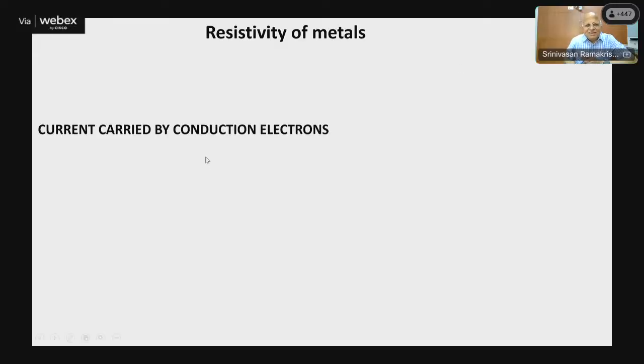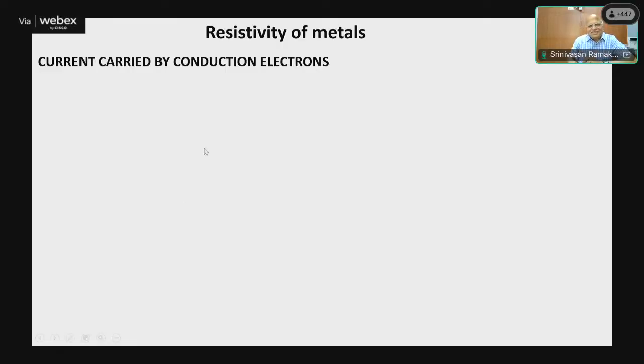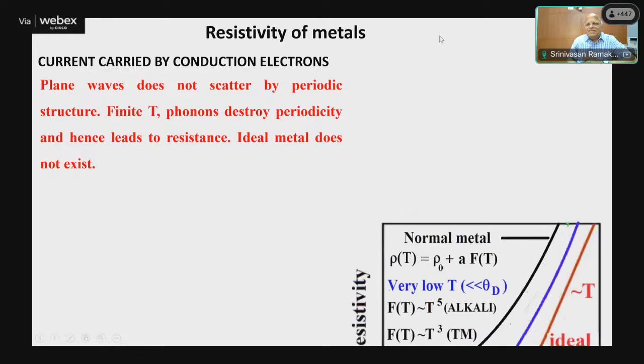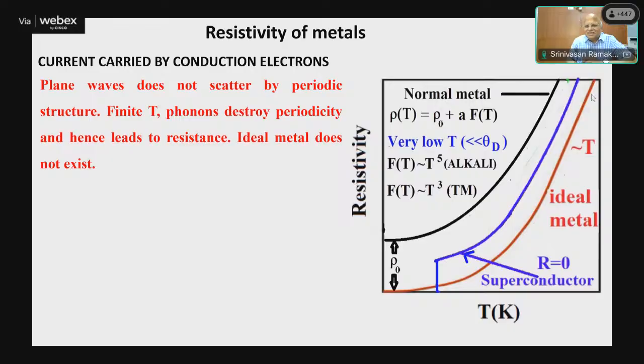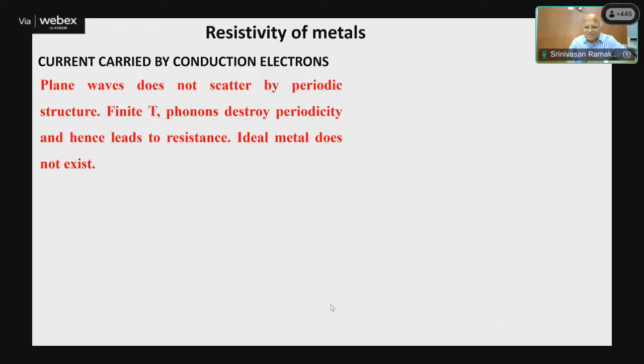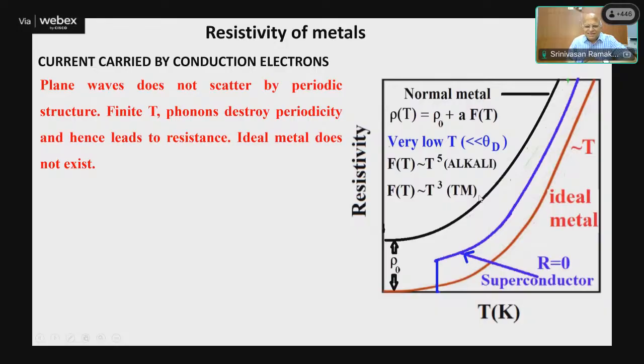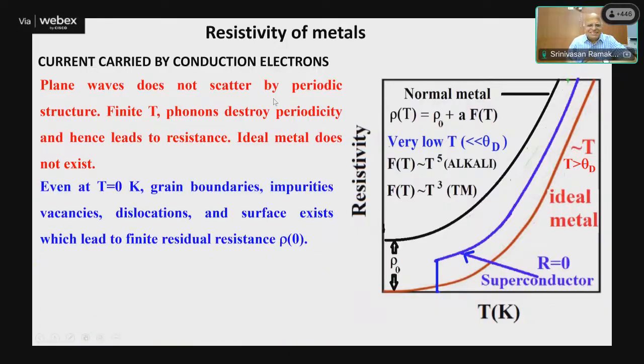And to understand superconductivity, let's look at the resistivity of materials. If you look at the resistivity of materials, the normal resistance decreases as a function of temperature. Then, depending on whether you have alkali or transition metals, the low temperature dependence goes as T to the power of 5 or T cubed. Whereas in a superconductor, it follows the normal kind of metal, but at some temperature, abruptly the resistance goes to zero. This is what distinguishes superconductivity from normal metals. Of course, the ideal metal is supposed to go like this, but that doesn't exist, because there are always defects, grain boundaries, dislocations, and so on that will give a finite resistance here.